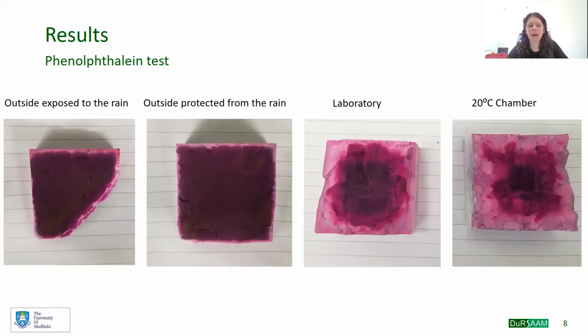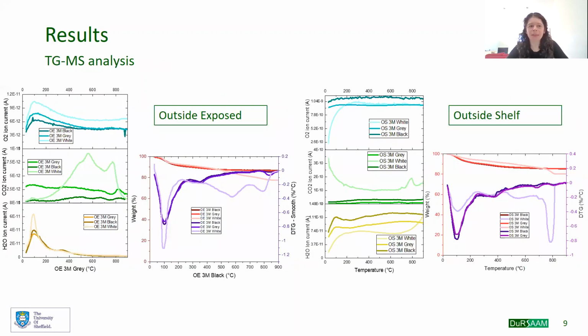But to confirm this, I did some thermogravimetry mass spectroscopy analysis. We cannot draw a conclusion from the oxygen mass spectroscopy, but we can see that there are 4 main peaks. The first peak is due to the water loss within the gel phases. The second peak is due to the hydroxide water loss, and the third peak is aragonite or vaterite, and the fourth peak is calcite, which is the more stable form of calcium carbonate.